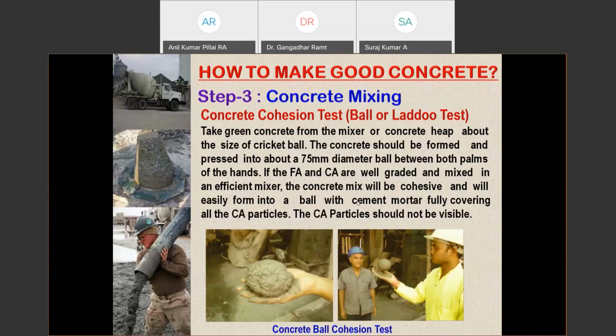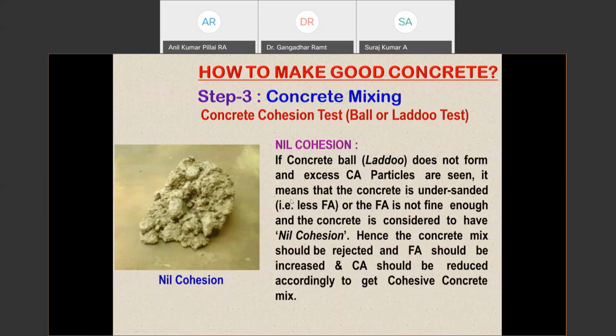Now there are certain cohesion tests he has recommended. He has talked about a concrete, what concrete we should say? We will say as nil cohesion. It says if the concrete ball or laddu does not form and excess coarse aggregate particles are seen, as in this figure, it means that the concrete is under sanded. Less amount of sand is there, or the fine aggregate is not fine enough, and the concrete is considered to have nil cohesion. This is not a good concrete. Hence, the concrete mix should be rejected.